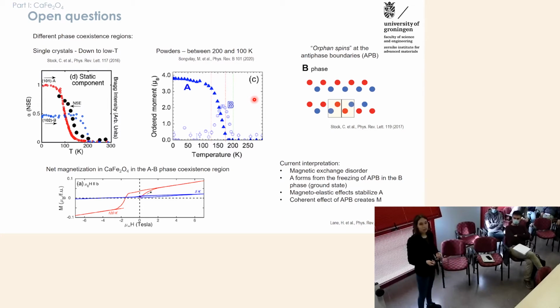What is not very clear about the system is how exactly the coexistence of these 2 phases works. Because, for example, if we look at neutron scattering data, we find that in single crystals, A and B are found to both coexist down to the lowest temperature at the same time, while in other measurements done on powder samples, the B phase seems to only appear around 150 K, while A seems to be the ground state at 5 K. So it's not clear if this coexistence is a first order phase transition, if it's down to low temperature or only limited to a narrow temperature range.